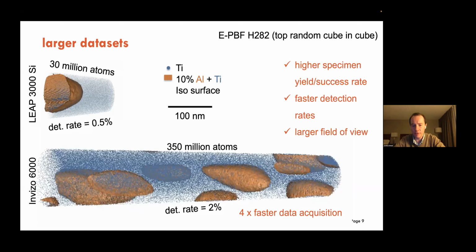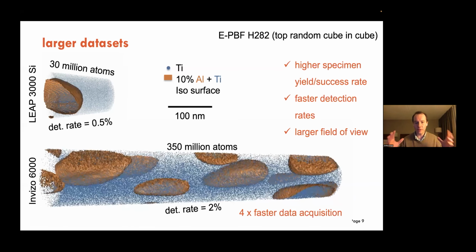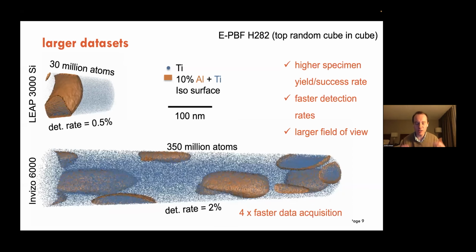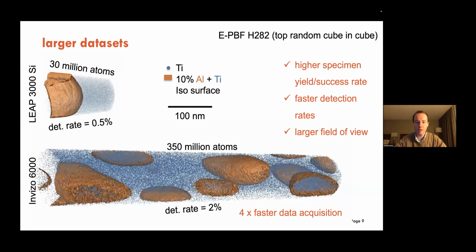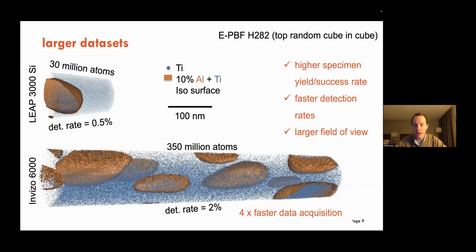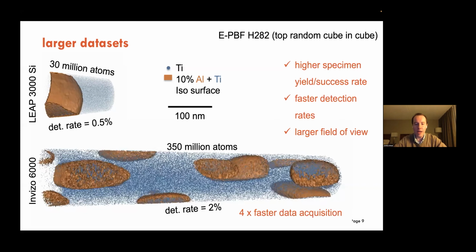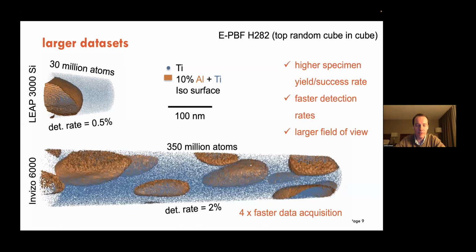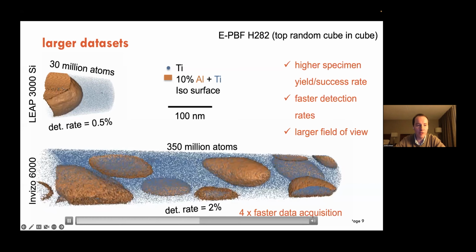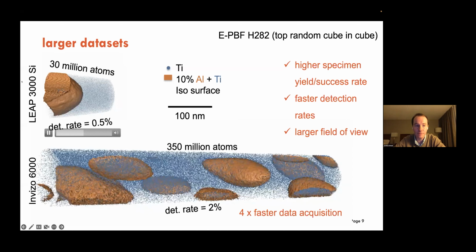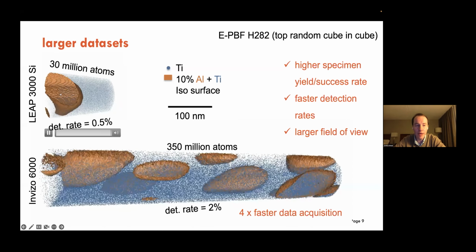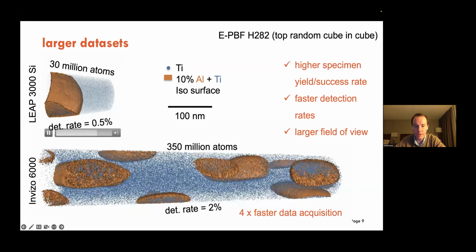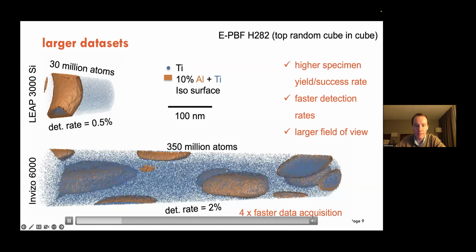We're also able to run at a faster detection rate, partly because of the larger field of view. So for the same equivalent stress on the tip, you can run at a high detection rate, but you can also crank that up a little bit higher due to the new laser technology there. And so we can get a significantly faster acquisition. And what's maybe interesting to note here is, at least on these length scales for the gamma prime precipitates that we see here in the LEAP, you're often going to get those precipitates being cut off. They're not just going to fit into the whole volume, whereas here you've got a much better chance of encapsulating a precipitate of this length scale within the reconstruction, which is nice.